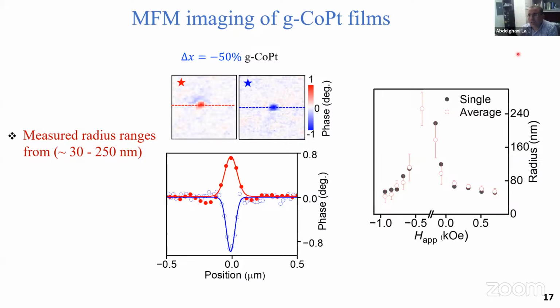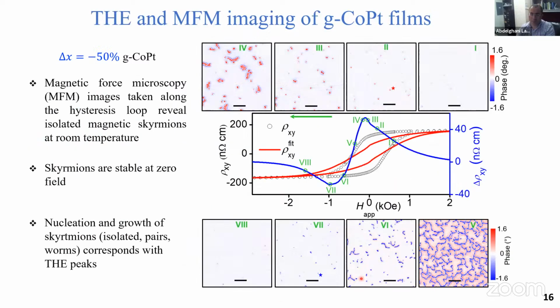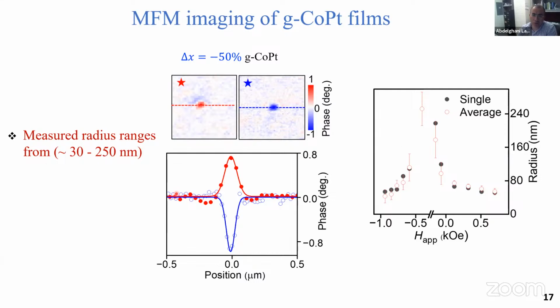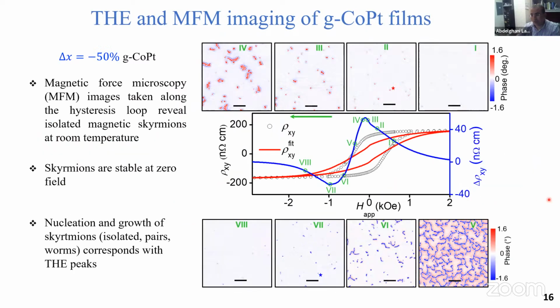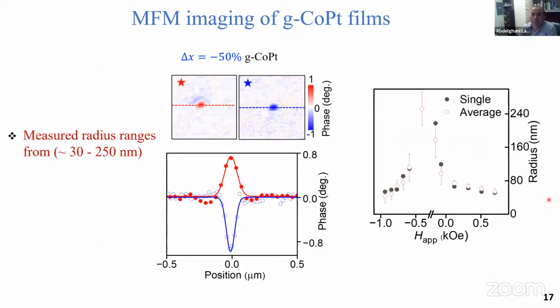We also measure, because this is an advantage of MFM, you can measure the size, or the radius in this case. We take the radius from a cross section of the positive or negative side of the magnetic loops. Using a Gaussian fit, we can extract the radius. Usually it varies from 30 to 250 nanometers. As expected, when you increase the magnetic field, you decrease the radius of the skyrmions. When you go to zero field, there is a formation of multi-domains, and then you go to the labyrinth kind of spin textures.